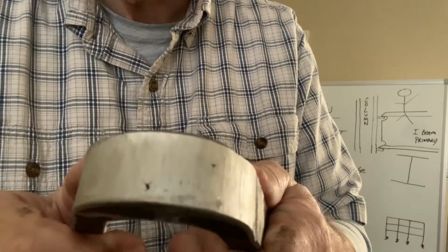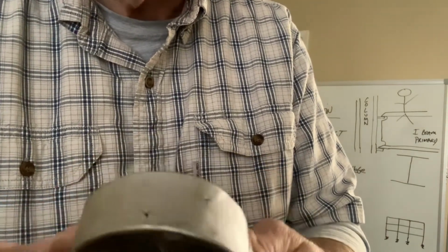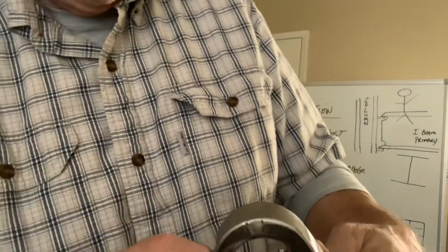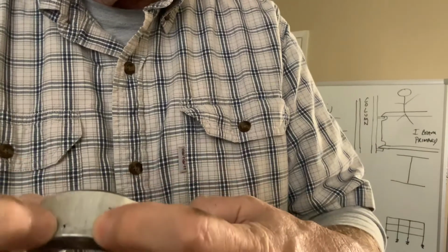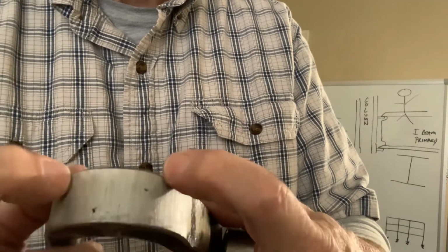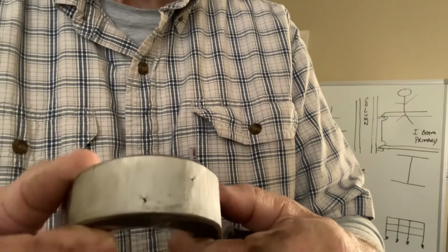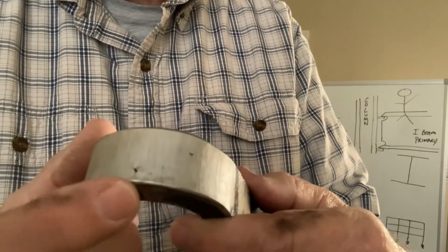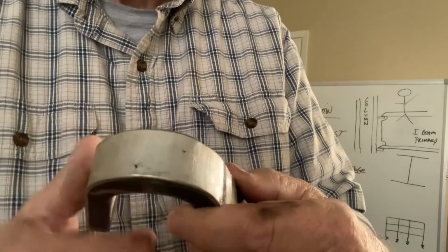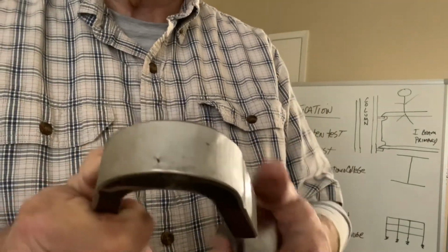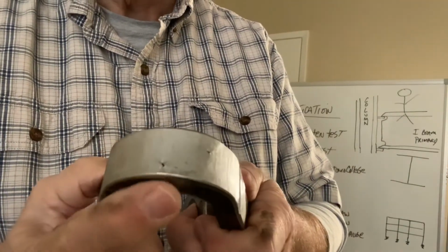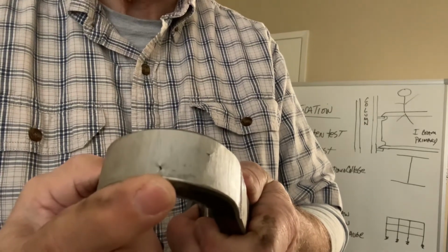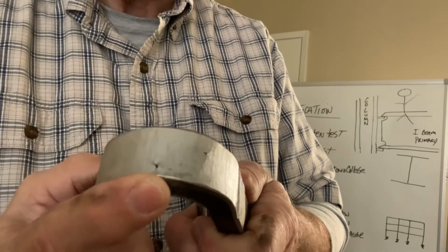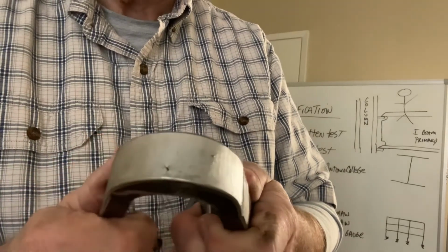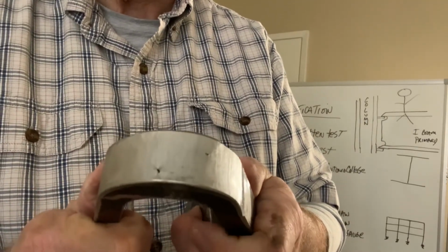And I picked this one because it had some discontinuities in it, and let's see if we can get a good view of the bevel of the plates right there on the side. I hope that you can see them in this view, but you can see the slight opening there. So what's allowed when you do these side bends, you're allowed anything up to 1/8 of an inch. Anything larger than 1/8 of an inch fails. Also, cumulatively, you're allowed 3/8 of an inch. So that's quite a bit.